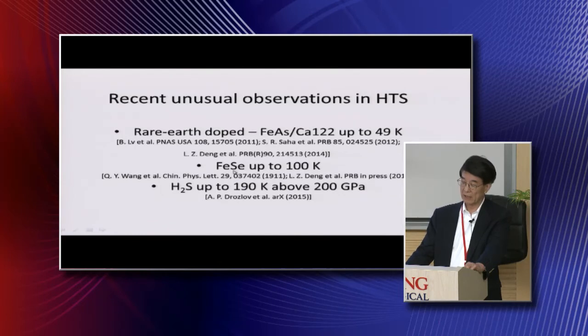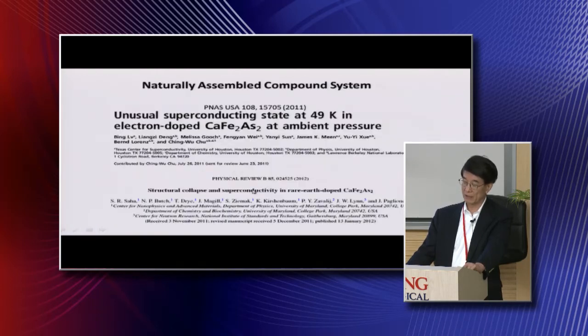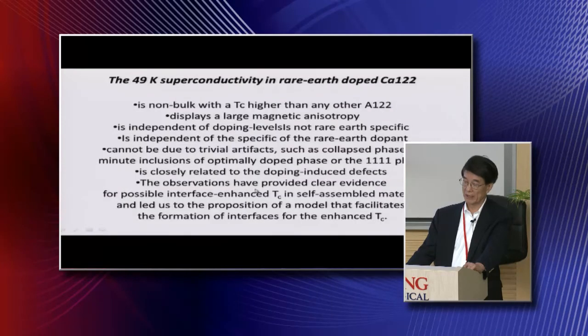And then in iron selenide, as done by Xue and co-workers, they found that the single layer material has a transition temperature at the beginning around 40 K and then later raised to 100 degrees Kelvin. And then, of course, the recent announcement of H2S under pressure up to 200 gigapascal, superconducting up to very high temperature. So we did all kinds of study. Because of time, I'll just briefly mention it.